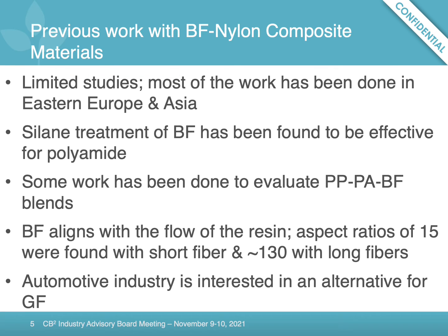When we reviewed the available literature, what we found was that very limited studies were done on basalt fiber nylon composite materials. These were done in Eastern Europe and Asia. Generally, the basalt fiber was treated with silane in order to provide a good interaction with polyamide. And there was some work done to evaluate polypropylene that was combined with polyamide and basalt fiber. And generally, people found that basalt fiber aligned very well with the flow of the resin, and the aspect ratios were much higher, about 130 when long fibers were used.